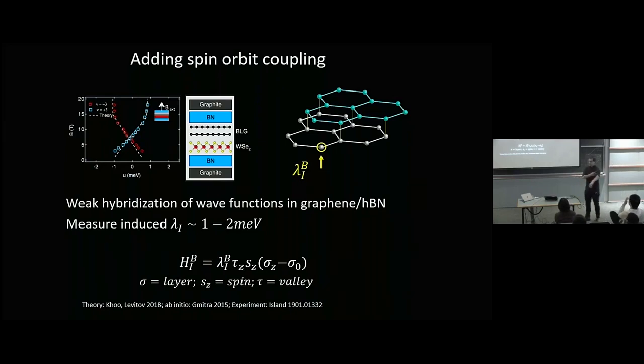WSe2 is a semiconductor, and the band alignments are such that when you put graphene on WSe2, most of charge neutrality and a good range around charge neutrality in the graphene is just in the middle of the gap of the WSe2. But there is some, maybe virtual, tunneling process where graphene electrons can jump into WSe2, spend a little time there, come back, and pick up some small fraction of the spin-orbit coupling in the WSe2. Now, what's really useful about Bernal bilayer graphene specifically is that you can measure the strength of the Ising spin-orbit coupling extremely accurately by some Landau level physics that I won't get into, but you can find in this reference.